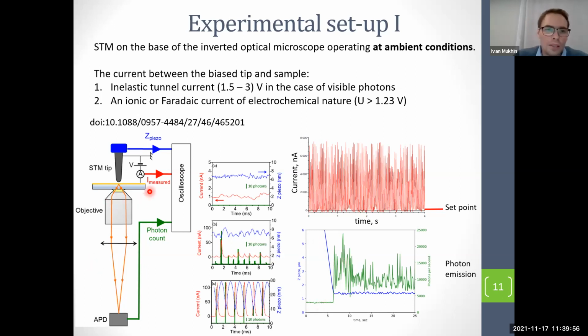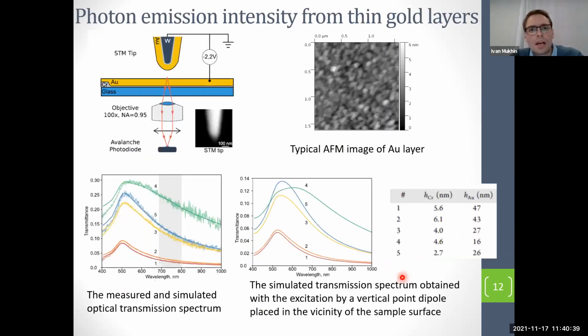Sorry, I forgot to mention that we use an inverted optical microscope combined with the STM. As a substrate there is a semi-transparent glass substrate covered with a thin metal layer, and we have an objective under the substrate, so we are able to collect transmitted photons through the semi-transparent metal layer. You clearly see that if we have an oscillating tunnel contact, we have a very nice optical signal. The first question raised was how the morphology of the metal film influences the light emission, the efficiency of inelastic tunneling, at ambient conditions.